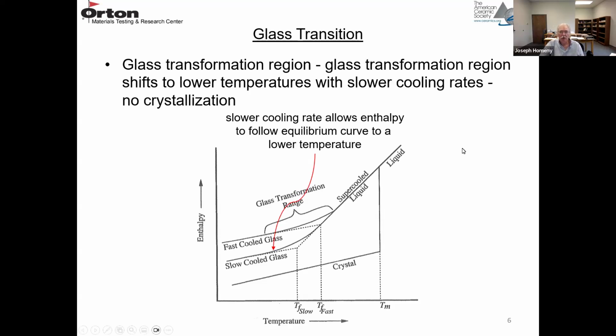And that glass transformation region is a function of the cooling rates. So the glass transformation region shifts to lower temperatures as you go to lower cooling rates. So this top curve here is for fast cooling. Here's your transformation range. And then the bottom curve is for slower cooling. So the transformation range is shifting to a lower temperature. So the slower cooling rate allows the enthalpy to follow the equilibrium curve to a lower temperature.